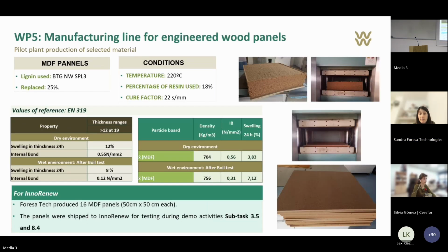In the same way, we elaborated an MDF resin, in this case with 25% lignin. With this resin, we were able to elaborate MDF panels that meet the standard. If we increase the percentage of lignin in these resins, both plywood and MDF, the panels we obtain do not meet the standards. That's why these two kinds of panels were chosen for the demonstration in this NewWave project.